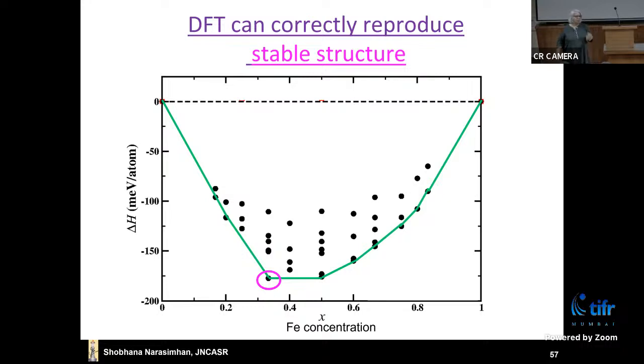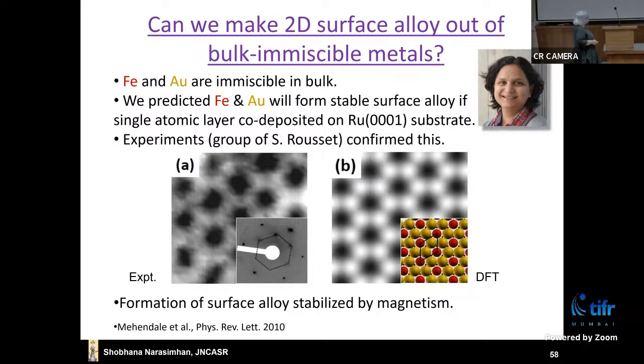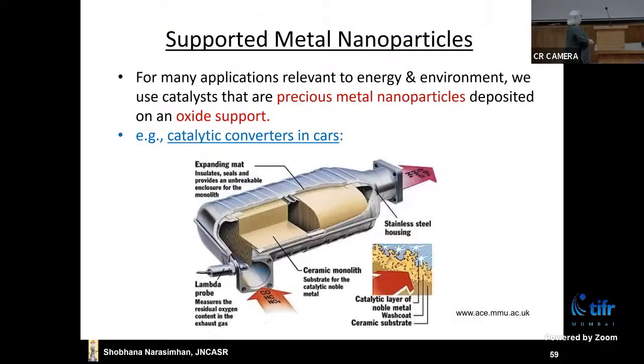Then the question is, why? Why is it that structure out of all those that forms? And why does it form? And this was again a real surprise, which you could only get out of the calculation, and it was a very unexpected answer. And we found that the formation of the alloy is stabilized by magnetism. So you know that iron is ferromagnetic. Now it turns out that in this particular structure, where every iron atom is surrounded by 6 gold atoms, the iron atoms acquire a very high magnetic moment. And then that lowers the energy of the system considerably, and that is why the alloy forms and why it forms in this structure. So this is an example of going back and forth, theory, calculations, experiment, and then making a new material. So I'll now go to another example.